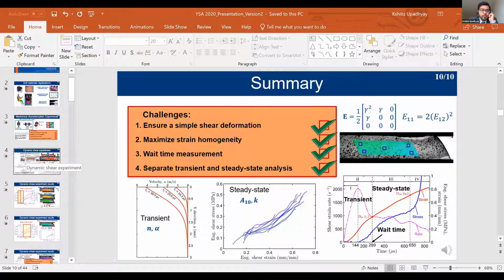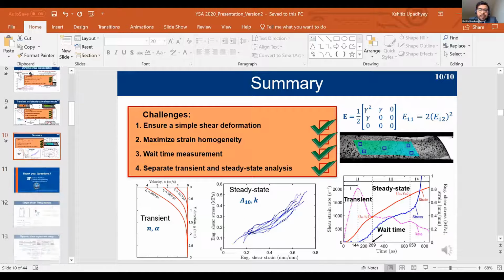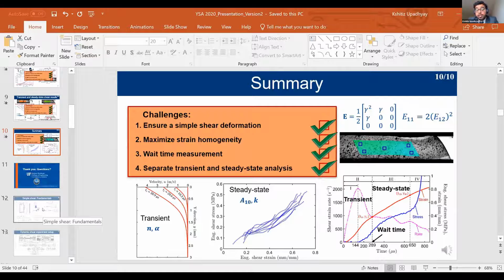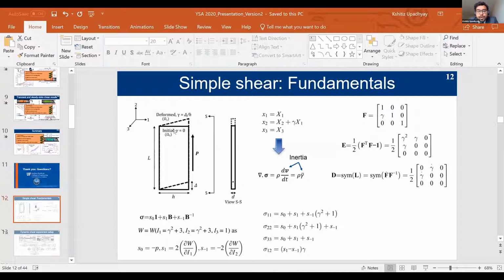Yeah, that's a very good question. And I think the acceleration is directly related to the strain rate. So if you look at this slide where I talk about the simple shear state, the acceleration in simple shear is rho times the gamma double dot component. So basically when I say that the strain rate is constant, I mean that the strain acceleration is zero, which means that gamma double dot is zero. The double derivative of the strain is zero. So that's what I mean when I say that the strain rate is nearly constant.